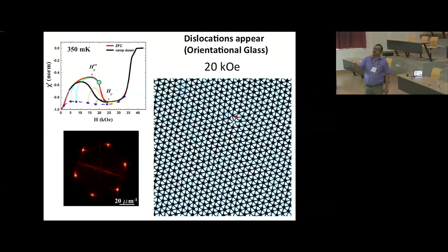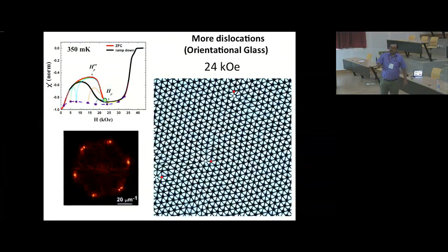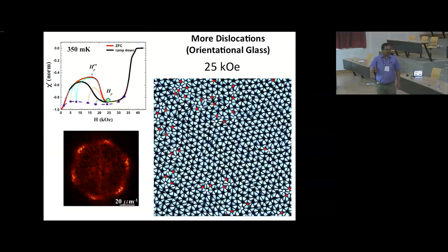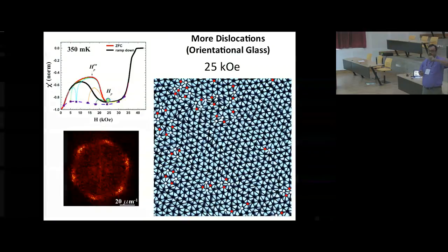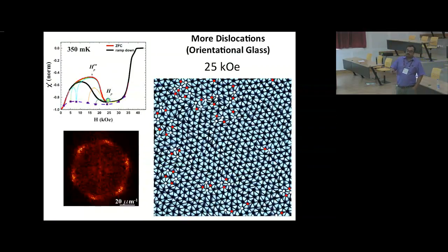I start getting these dislocations. These dislocations are adjacent points with 5-fold and 7-fold coordination. I go to higher field, more dislocations. Here I have even more dislocations. But please note one thing, dislocations do not destroy my orientational order. So in the Fourier transform, though the Fourier spots get broadened, they still retain the 6-fold orientation. So the 6-fold orientational symmetry is retained.